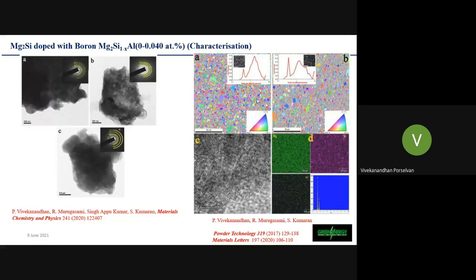And then we can compare with the very, very tiny scales that are widely spread in the bulk material. This is a bulk material EBSD graph. It will give you a good idea. And this is a TEM image, which shows the crystallites that have nanoscale size. Here the scale from here to here is 5 nanometer. Then we can understand that the crystallites available in the bulk material are less than 5 nanometer. And these EBSD graphs confirm that the Mg2Si and the so-called dopants are uniformly distributed.